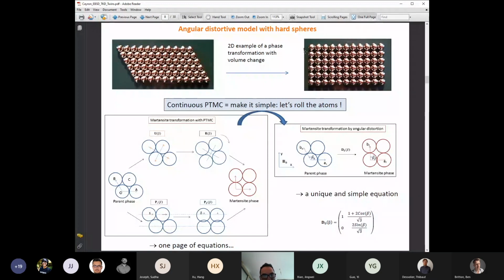So if you just look at these two images, you can tell, no, the atom rolls, and let's look at how they could move. It's not as complicated as PTMC tells. It's what I try to say at the right here, where you just imagine that you move the atoms. I had a movie to show, but you can imagine you just let the atoms roll, and you can do math. You can calculate a distortion matrix that depends on the angles that are called beta here, and you just change the angle beta, and you go continuously from the left to the right, from the hexagonal stacking to the square stacking, without any difficulties, actually.